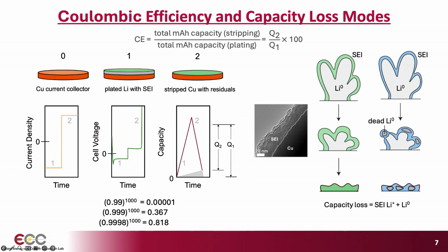And the demands on reversibility are extraordinarily high. So for an electric vehicle battery, we need to cycle 1,000 times, and typically we want to retain 80% of the energy density over that lifetime. So even neglecting any voltage fade, and just considering capacity fade alone, you would think that something like 99.9% sounds really high for a single plating and stripping step. But if you do that 1,000 times, you're left with only 37% of your active lithium inventory by the end, okay? So you really need to be at 99.98%.